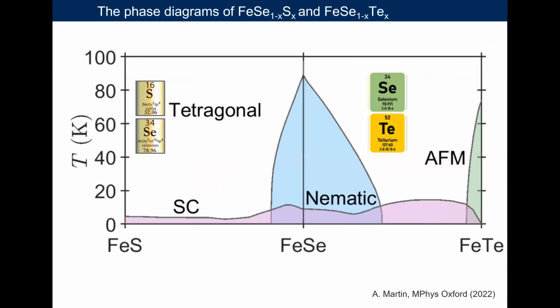So I will focus on the ARPES data in these two families of compounds as we suppress nematicity with both sulfur and tellurium. And already we can see here that there is some asymmetry between the two sides. Here the system eventually becomes more localized, and here it is much more metallic and correlations are weaker.